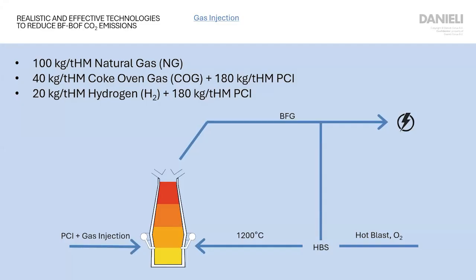Second, we've been assessing the impact of using coke oven gas instead at a moderate rate of 40 kilos for 1 ton of hot metal, and another 180 kilos of PCI. You may wonder why 40? Well, we have come to realize that the availability of coke oven gas on its own is limited by the coke making plant. And some coke making plants may produce more coke oven gas, others may produce a little less, but we believe that a moderate average number for our industry would allow usage of approximately 40 kilos of coke oven gas for each ton of hot metal, as we also need to use minor amounts of coke oven gas for enrichment in hot blast stoves, but also for heating in the reheat furnaces.